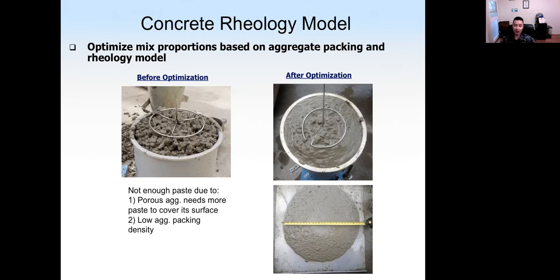Okay, that's not enough cement paste because our Hawaii aggregate is very porous. So that means we need more cement paste to cover the surface of the aggregate. And also the packing density of our local aggregate is lower. That also translates into more requirement for cement paste. So after the optimization of this mix design, the concrete becomes flowable again. Okay, as we can see from here.